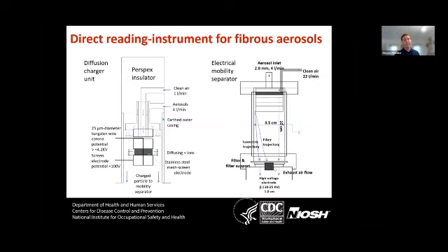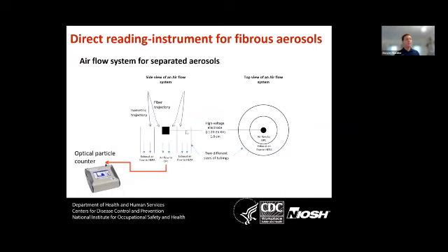If we turn this into, rather than a filter, a pathway, then we can look at the fibers that are getting through the center of that area, and then we can count them using any sort of optical particle counter. So this would be the idea that you could put on a worker. We could miniaturize it to put on a worker, and what we'd be counting is only the fibrous particles. So that would be the idea behind our direct reading instrument for fibrous aerosols. And again, these are all just beginning research.